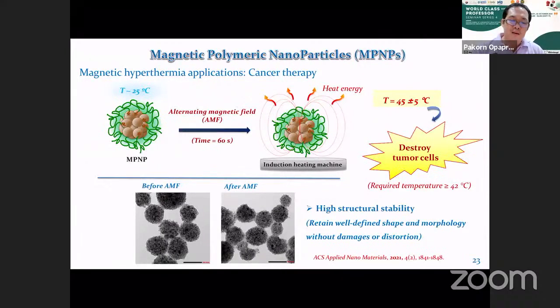So what about the responsive properties? If we apply an alternating magnetic field, or AMF, to this type of material using an induction heating machine, we can heat up the magnetic particles inside the polymer particle to a very high temperature. As a result, the heat is transferred to the polymer and the temperature of the whole particle increases.